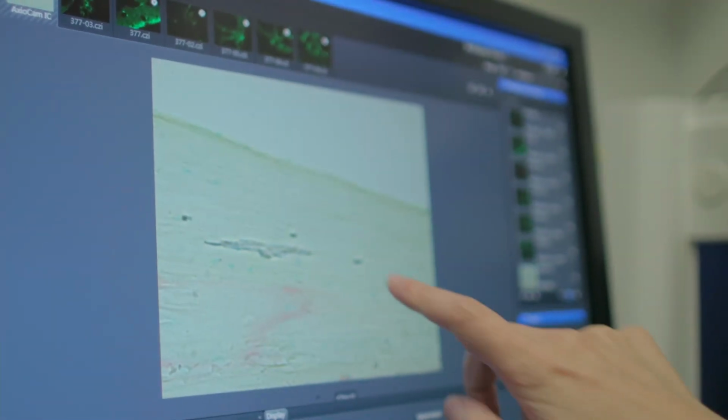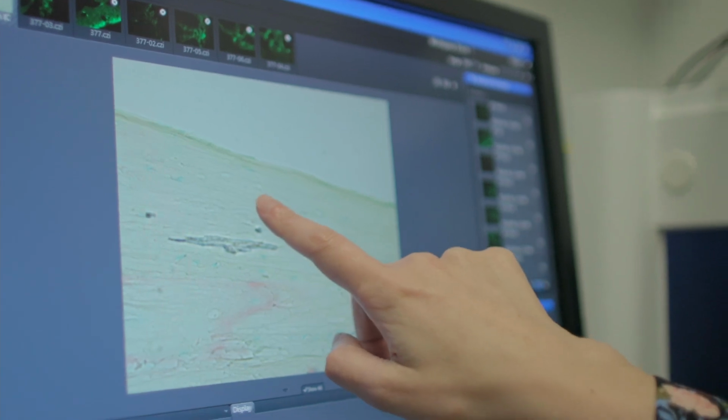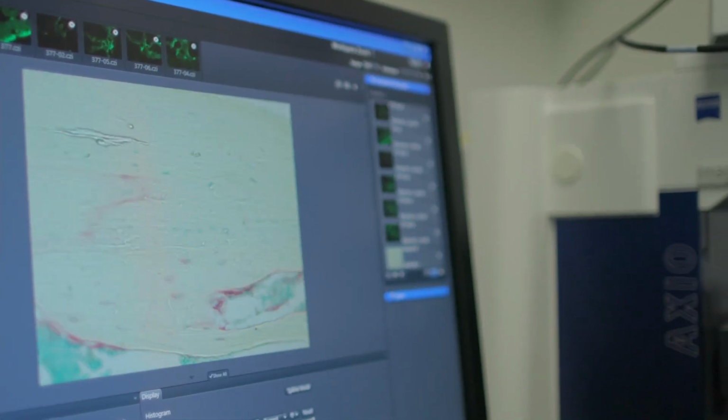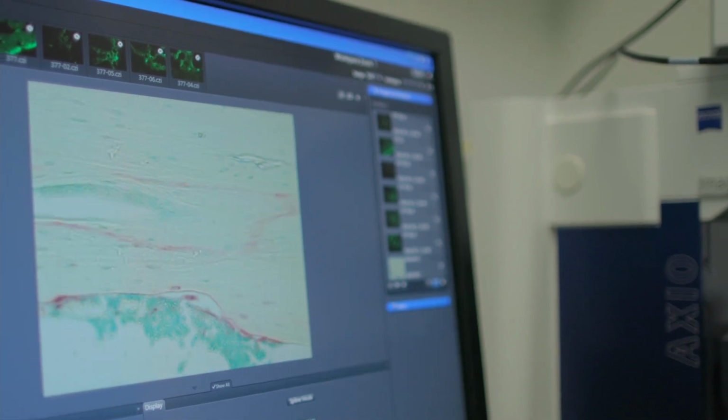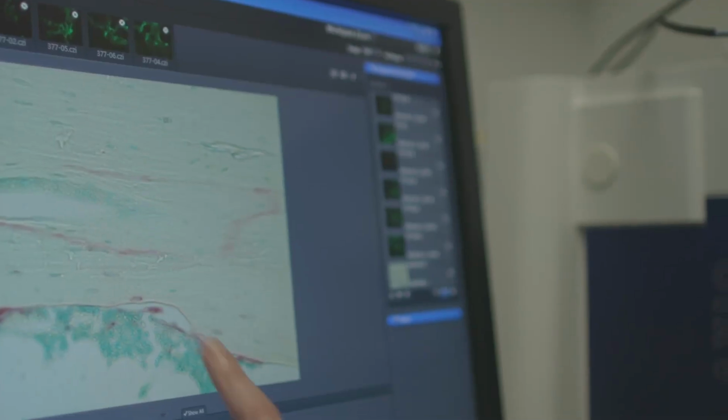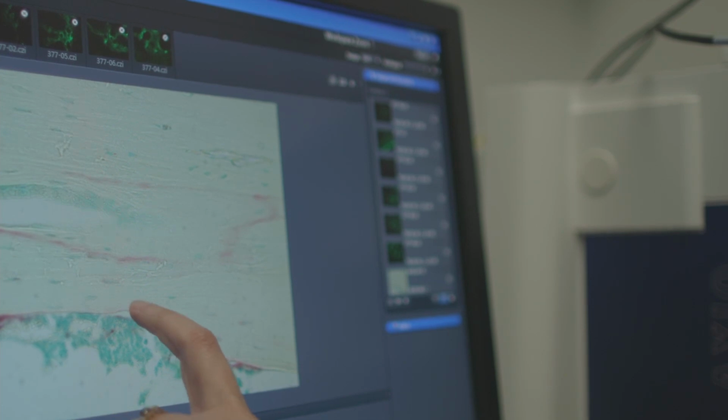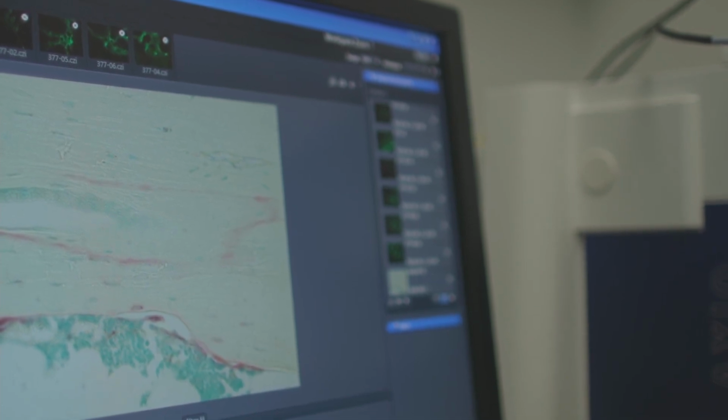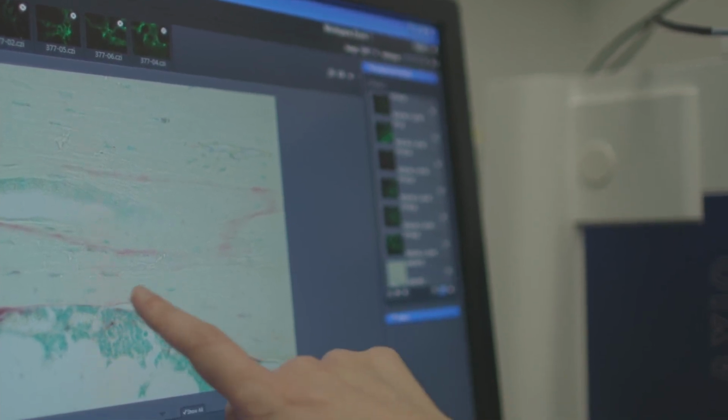With this, we can also do higher resolution scans and look at spatial patterns in the pores, which is where the cells sit, and look at connections and patterns in these pore spaces. So the macroscale geometry will be at the millimeter scale, and then some of the tissues will be closer to tens of microns, and the pores will also be quite small, pushing the resolution of the micro CT.